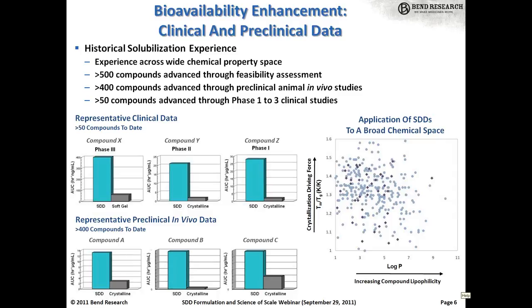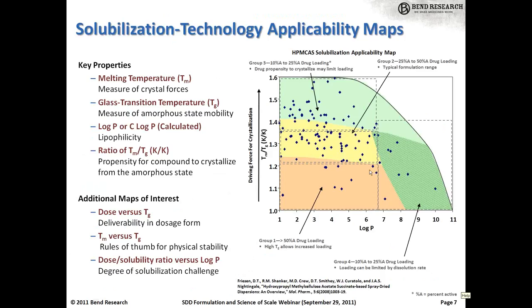Okay, so this just kind of highlights a little bit of the performance advantage and experience with spray-dried dispersions. They've been used extensively by ourselves and others, both in preclinical and clinical studies to provide greatly increased exposure relative to crystalline drug or other dosage forms. And there's some examples shown here of clinical data as far as late phase 3, showing the increase in AUC for SDD relative to even a soft gel or crystalline comparators, and then just a few examples of preclinical species. So the technology is pretty well precedented for a pretty broad array of drugs from chemical space. And there's a simplified map of chemical space that sort of illustrates that here. I'm going to touch on that more here on this slide, so we'll move on.